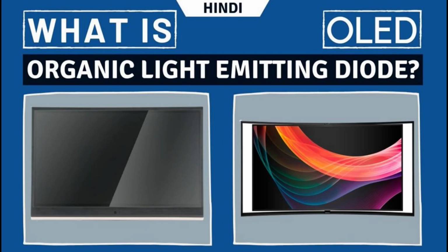Proper encapsulation is critical for prolonging an OLED display's lifetime, as the OLED light-emitting electroluminescent materials are sensitive to oxygen and moisture. When exposed to moisture or oxygen, the electroluminescent materials in OLEDs degrade as they oxidize, generating black spots and reducing or shrinking the area that emits light, reducing light output. This reduction can occur on a pixel-by-pixel basis. This can also lead to delamination of the electrode layer, eventually leading to complete panel failure. Degradation occurs 3 orders of magnitude faster when exposed to moisture than when exposed to oxygen.